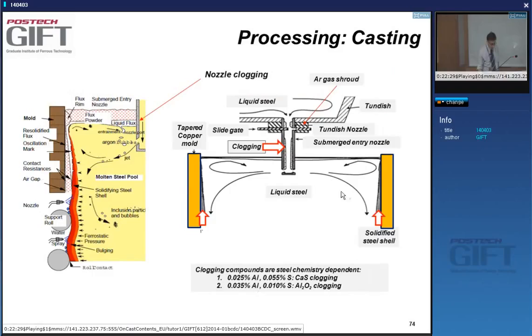Very important to remember here, a critical thing is that you want to have a shroud here. The clogging I was mentioning on Monday, this is where it occurs, in the submerged entry nozzle. You can see that if you have large deposits of solid on the inner tube wall, the amount of steel that comes out will be influenced, and so you'll have an unstable casting.